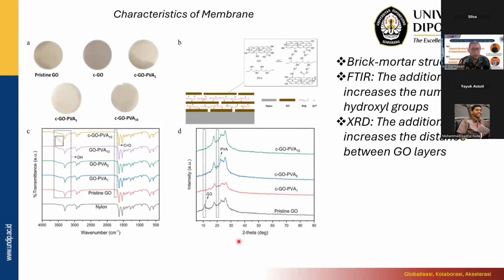Yeah. Okay. The next one is we already synthesized the GO. We mix the GO as a membrane with the PVA, polyvinyl alcohol, and the structure we call the brick and mortar structure. This is like brick, and it's like the mortar in the building, right? What is the function of the PVA? We put the PVA to inhibit the swelling of GO, because the GO is actually easily swelled if we infiltrate water in the middle. Yeah, so the PVA inhibits the swelling of the GO.